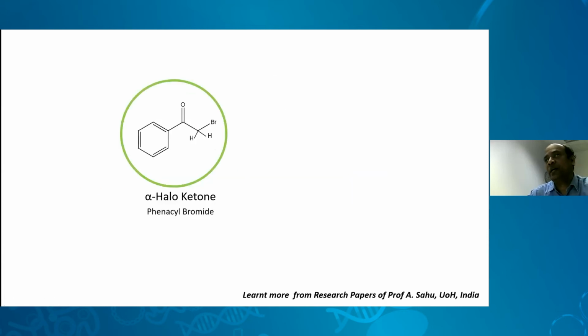We found an alpha haloketone, a well-known organic molecule. This type of material we have used, and in the presence of amine it undergoes a substitution reaction, SN2, giving a bulkier ligand, which is larger in size than that of A. That was our aim. However, we obtained this one. Actually, it was accidental, but whatever final ligand we received served the purpose.